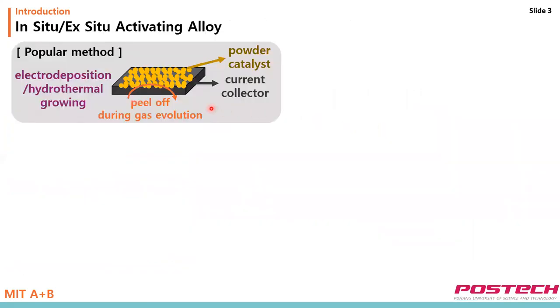So many preceding studies have suggested that various transition metal-based powder electrocatalysts are loaded on conductive substrates by electrodeposition and hydrothermal growing methods. These attached catalysts can easily fall off from the substrate during dynamic gas evolution. Therefore, to adopt in real application, electrocatalyst stability is a growing problem.